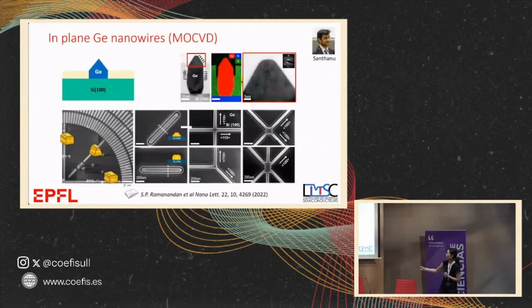So how do we do this? At the same time, we looked at the orientation dependence, and we grew this time with MOCVD the germanium in selected areas. And this is what we wanted to have, this shape. And this is the first material we made. So they were a bit longer than we wanted, but you see that in the tip they're single crystalline. So we have very high quality. We can also make these networks as we had before, which is necessary for having some logic.